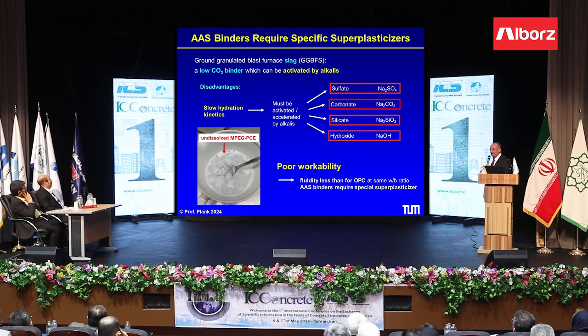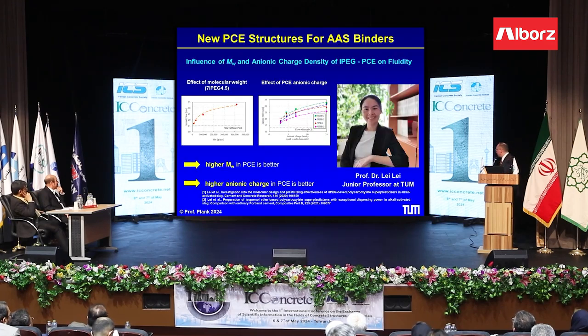Now, a problem with slag cements is we need alkaline activators to get early strength, like sodium sulfate, carbonate, silicate, sodium hydroxide, and we use them in a relatively high concentration, like 2%, 4%, 8% even. And in these activator solutions, normal PCEs are not soluble. And if they don't dissolve in the water, they cannot be active as a superplasticizer. So when we use these binders with these activators, we need new superplasticizers. And Dr. Lei Lei, when she did her habilitation in our university, she was a junior professor there, she worked on IPEG or TPEG PCEs, which dissolve in these activator solutions and are effective.